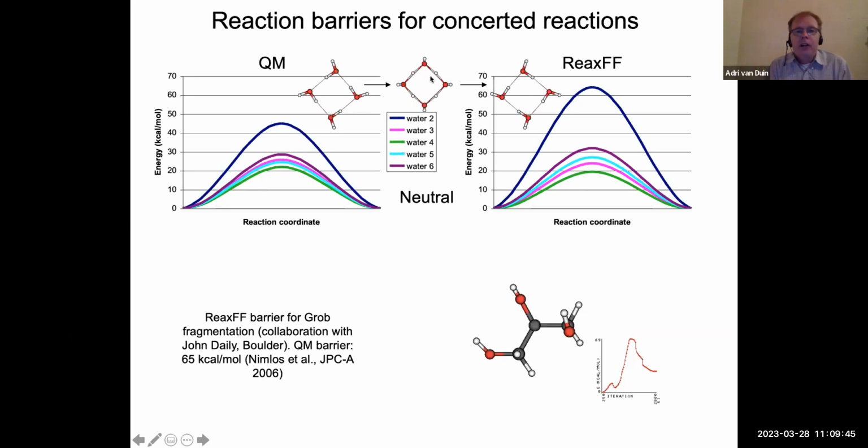They tease water molecules into the right configuration and then can break relatively strong bonds at a very low energy cost. Here, this reaction has a barrier of only 20 kcal, and remember that each OH bond is worth about 125 kcal, so roughly 5 eV. And so we indeed can do this reaction at a fraction of the sum of the bond energies, only 20 kcal. So this is actually a reaction that can happen at room temperature.